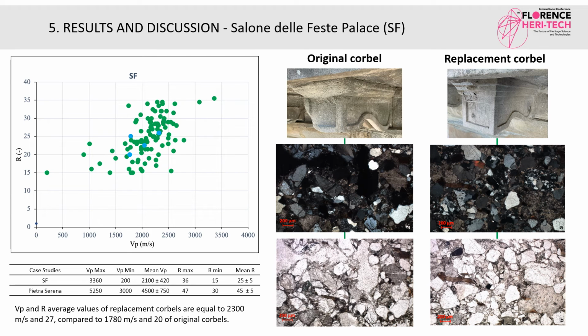The replacement and original corbels were analyzed. The sandstone used for the substitution campaign shows a higher amount of microsparitic calcite cement, unlike the original sandstone that has a lower amount. Nevertheless, both sandstones have medium high porosity. The Vp and R values indicate lower mechanical properties and poor state of conservation in both replacement and original samples. However, the higher values of replacement corbels are probably due to the high amount of calcite cement.